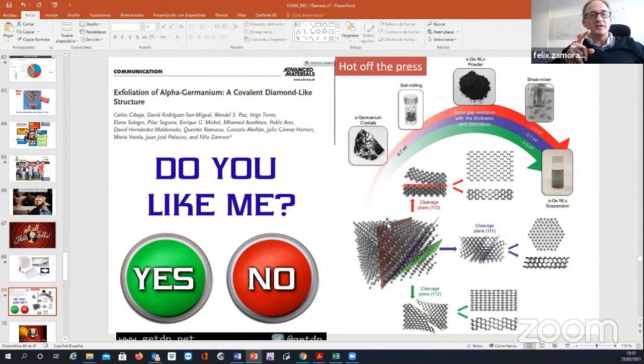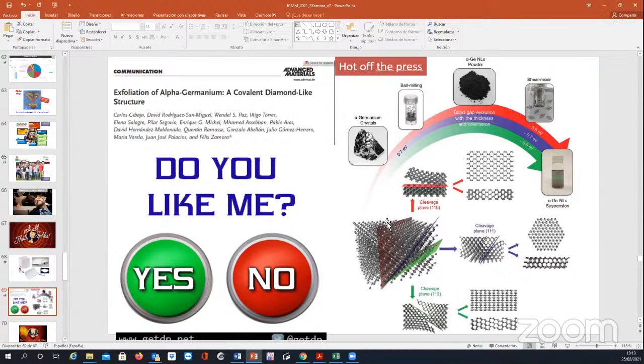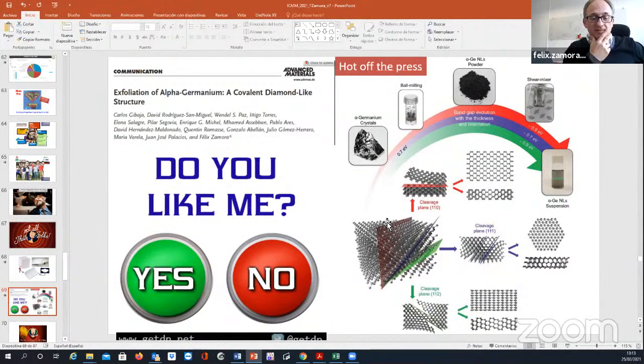We tried to do the same with the following element. I mean, the one on the top. We tried to do the same with silicon. And what we found is what you said. We were able to have just a slight difference between the lateral dimensions and the thickness, as small as 1 order of magnitude. And we couldn't adjust all the parameters.